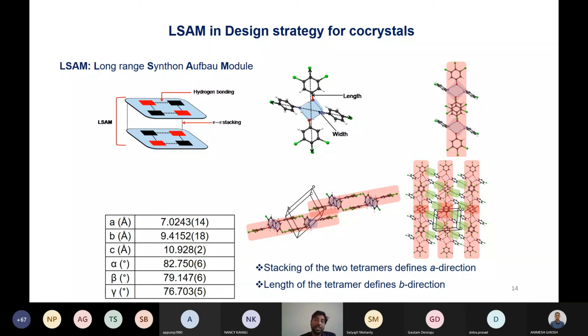many structures with this tetrameric hydrogen bond in the aminophenol family. And there is also a propensity of this pi-pi stacking in 1,2,3-trichlorobenzene or 3,4,5-trichlorophenol. So we combined these two aspects in this series of crystal structures, and we obtained crystal structures with controllable dimensions.